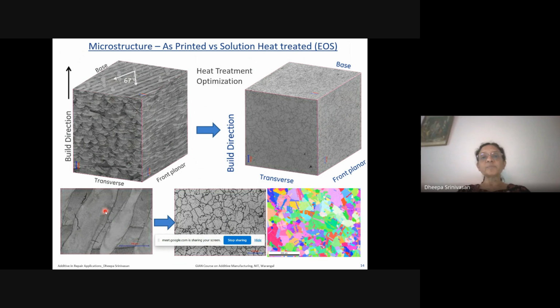However, in principle, we had to heat treat the samples, because remember, we were going to do a weld repair, which means you need to do a pre weld and a post weld heat treatment. So as part of the master's thesis, Kaustubh tried a bunch of heat treatments, and the heat treatment resulted in a microstructure which ended up with a beautiful uniform recrystallized microstructure. You can see some very fine grains out here. This is blown up out here in the lower pictures.